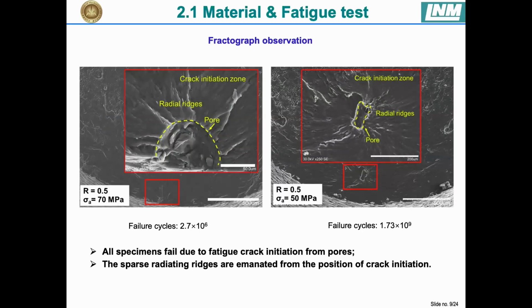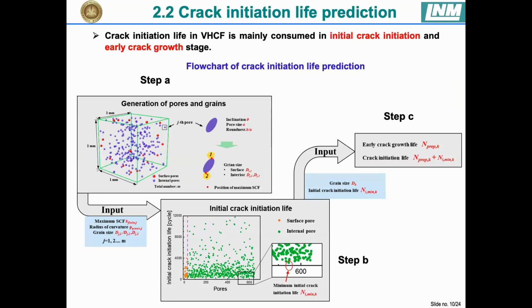Then the fractography observations show that all specimens failed due to fatigue crack initiation from pores, and it can also be found that sparse radiating ridges exist near the crack initiation position. Therefore, in very high cycle fatigue, the majority of fatigue life is consumed in the crack initiation life, and in the crack initiation life, it is mainly consumed in the initial crack initiation and early crack growth stages.